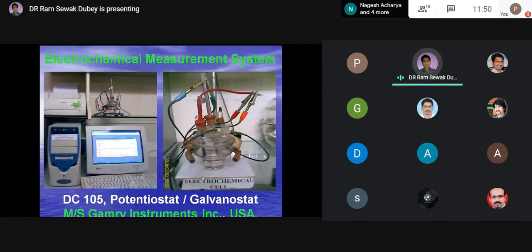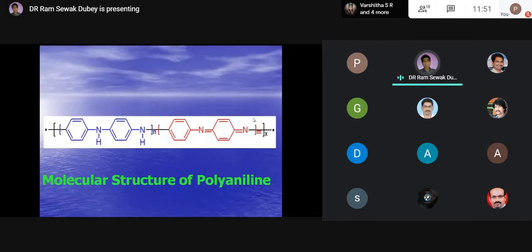This is the structure of polyaniline that was synthesized with the help of the cyclic voltammetric technique. A suitable potential range was selected. The details are shown here: the solution was 0.1 molar H2SO4, and the monomer was 0.1 molar aniline solution. By selecting the appropriate cycles of cyclic voltammetry, it was scanned between -400 millivolt to 100 millivolt with respect to the saturated calomel electrode, at a scan rate of 50 millivolt per second. This diagram shows the different peaks observed during the cyclic voltammetry experiment, and the cyclic voltammogram is shown here.